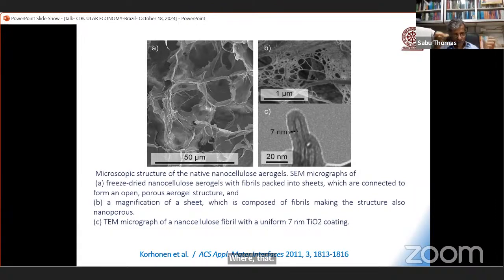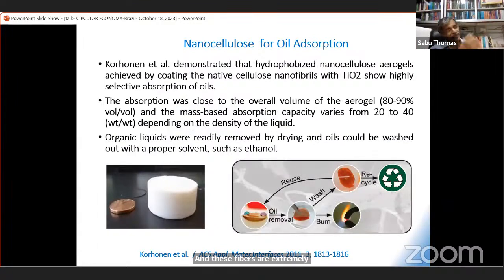Why did they do the coating? Because to make it hydrophobic. Once you give the coating, you see these fibers become hydrophobic. And these fibers are extremely porous. So once you make the surface of the aerogel hydrophobic, you put it in seawater. And when you put it in seawater, what happens? This red is the oil. All oil is absorbed by the aerogel because it's hydrophobic, and it's porous for the capillary action. All the oils could be absorbed.